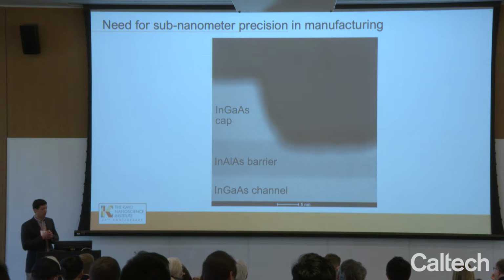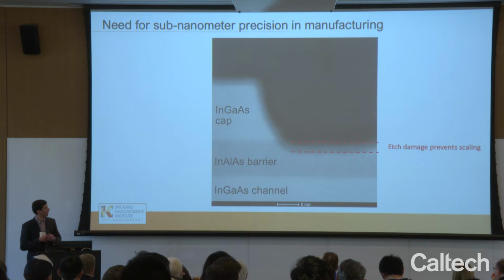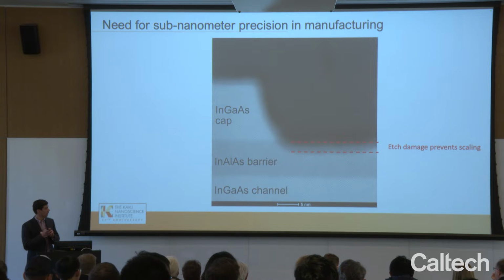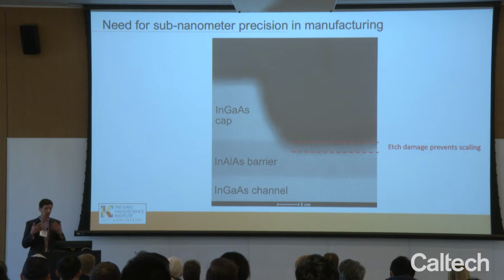And you can see that in the process of doing this, we lack the capability of this fine degree of control over the material structure. So have a look at this image. You see on the one hand these nice atomic columns, which are the shiny dot regions, but you also see this fuzzy region. This fuzzy region is essentially etch damage. When we pattern, we use liquid etchants or plasmas that impart damage to the semiconductor, which ends up as this amorphous fuzzy region you see in this image.